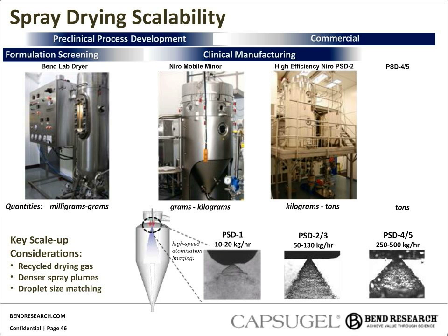So on the atomization front, in order to match droplet sizes across scales, higher nozzle pressures are required. And again, this should be evaluated early in development to ensure that a target SDD particle size is selected that can be achieved on larger scale spray dryers. So we use the nozzle test stand to help us do that.